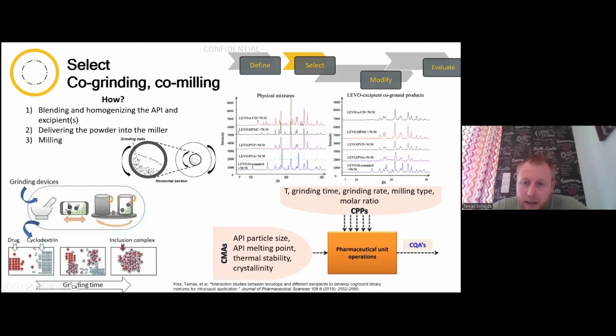And theoretically, when you look at the spectrum of the active ingredient and of the complex, in an X-ray, for example, the original crystallinity characteristics of the actives should completely disappear, and only the amorphous nature of the cyclodextrin and of the complex should be shown.